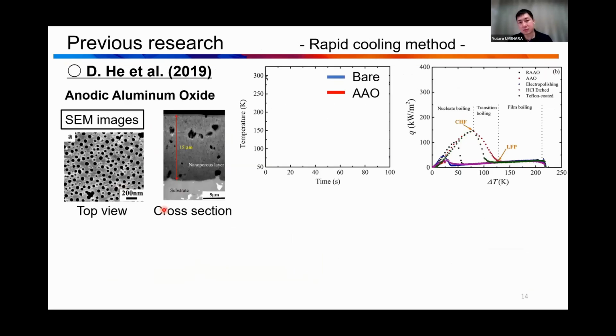So, previous research reported improving the rapid cooling method and the cooling duration when using cryogenic liquid. They reported anodic aluminum oxide on an aluminum substrate. They added the anodic oxide, and this nanoporous layer is very important to the enhancement of the cooling phenomena.